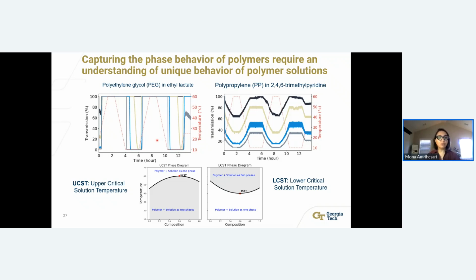Just looking at these two examples, you will see that these polymers go back to 100% transmissivity for all concentrations, despite the concentration going up. At higher temperature, while this example is not reaching 100%, it is progressing in this solution. So these differences between the systems make it very fun and interesting to navigate and find a standardized method with which we can measure the solubility of the polymer.